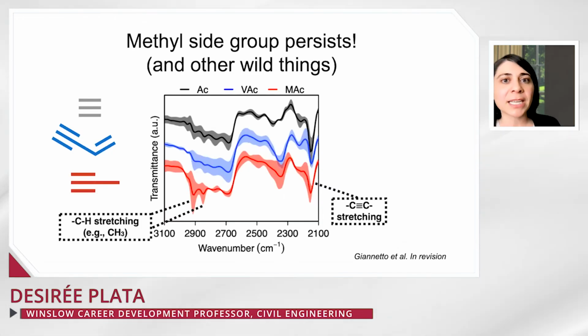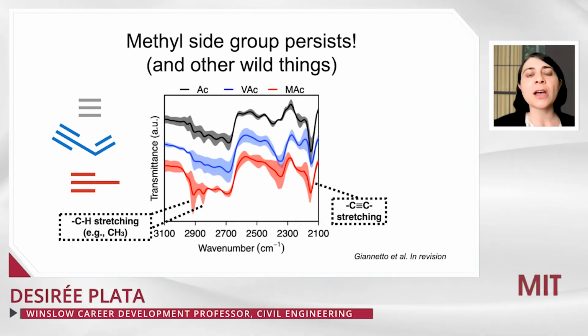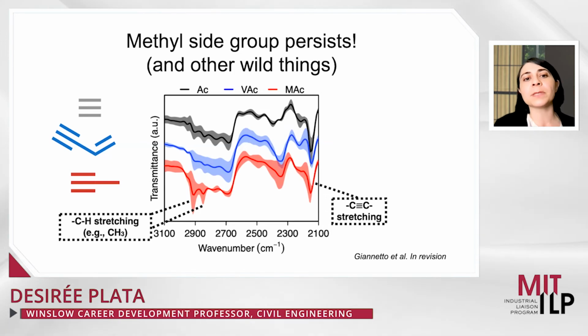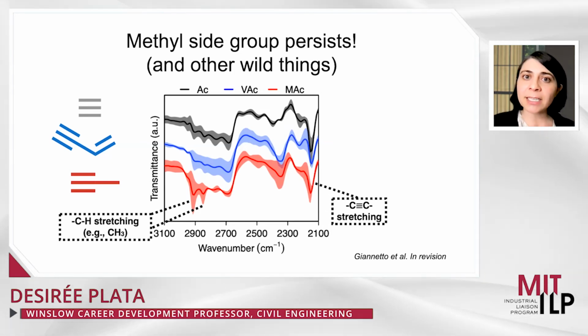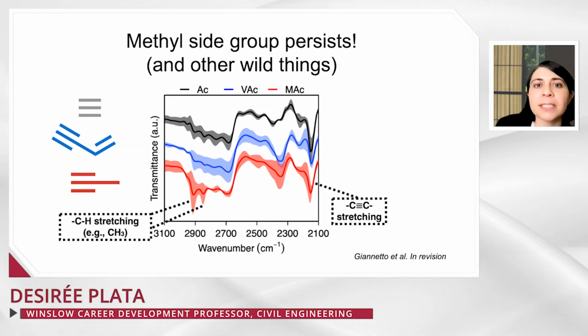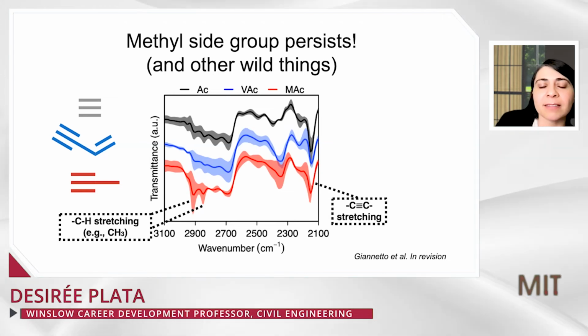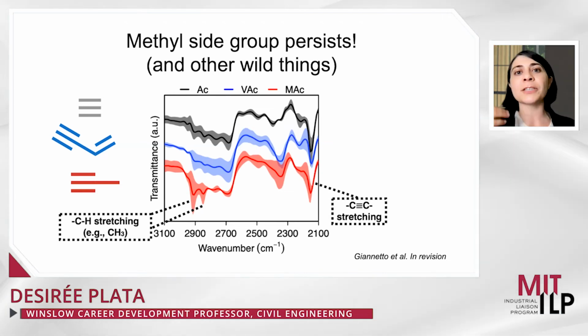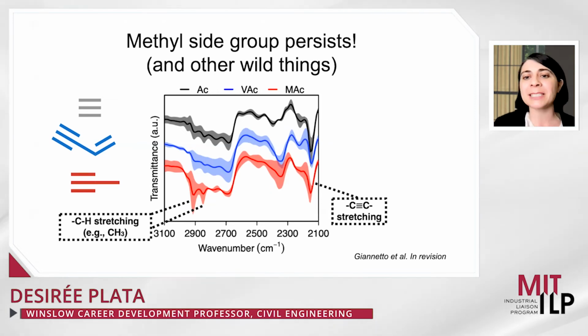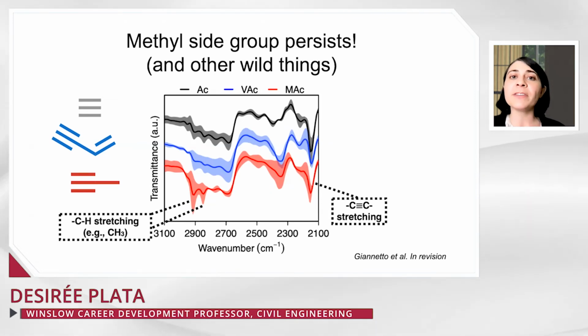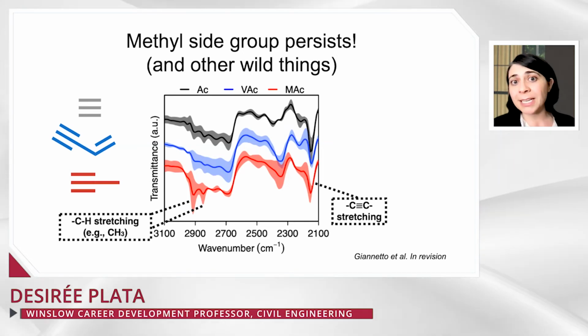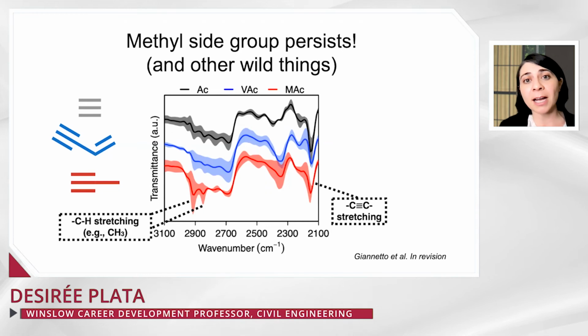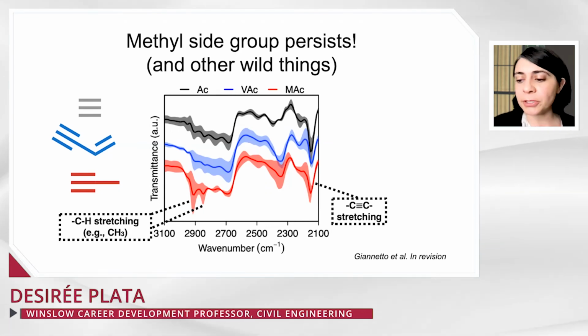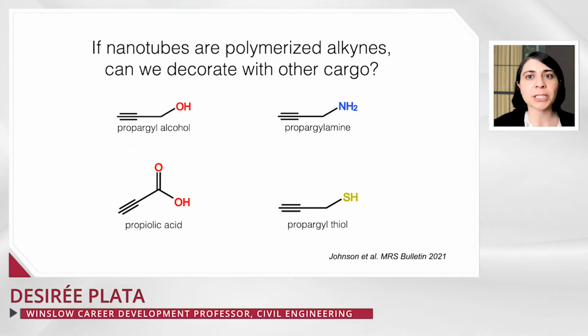The other thing that we were able to image in situ in intact structures was the existence of the methyl groups themselves. So what I'm showing you here is an acetylene grown forest, a vinyl acetylene grown forest, and a methyl acetylene grown forest, and their respective error bars for replicates. This is not just one sample, but many, many samples. And what you see is the emergence of an indication of the existence of methyl side groups in the carbon nanotube structure. This was really exciting. We also see things like persistent alkyne bonds in solids, which opens up a world of possibilities for manipulating the structures themselves and doing point-directed functionalization.